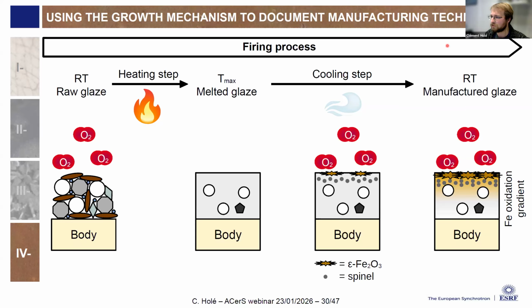And this is the opportunity I had at ID21 during my postdoctoral fellowship. So here is a summary of the firing process of brown glazes. First, we have raw material, so many different types of crystalline phases that are applied on the body. They are heated, so most of them melt, some of them stay, new phases can grow. And when we cool, we reintroduce oxygen in the kiln, and this will spark at the surface the growth of iron epsilon oxide, and below, a layer of spinel.